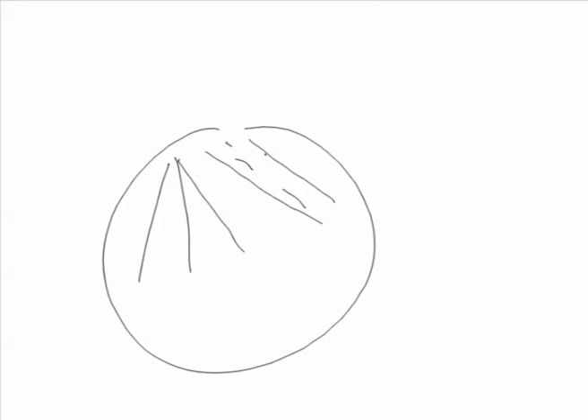Basically chevron marks are observed on the fractured surface, and the direction opposite to the chevron marks indicates the direction in which the crack has grown during the failure, and these chevron marks basically converge towards the location from where the fracture has initiated. So these chevron marks can be shown in this form. Say this is the component, then the chevron marks will appear in this way. These can be in the form of fragments like this. So the chevron marks indicate that the fracture has initiated from this location and it has grown in this direction. But these features can be observed only at low magnification, using macroscopy,